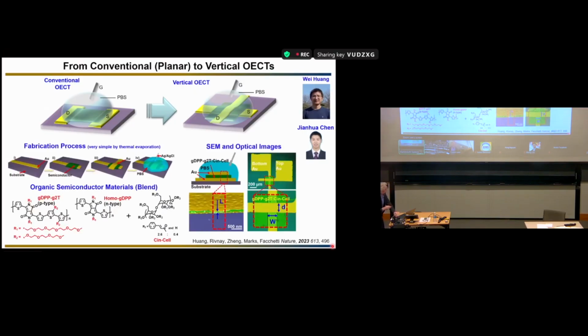So we made devices in the lateral architecture and in the vertical architecture, which is basically an array of gold crossbars, with the same semiconductor sandwiched in between, here in light green. This shows how the device is made. We deposit by thermal evaporation a gold line, then the semiconductor, then a second gold line, and we put the electrolyte on top. This is the cross-section SEM of the device, which shows the window through which the ions have to penetrate. The thickness you see here is on the order of 80 nanometers, so a very small window. This is the top gold, and this one is the bottom gold.